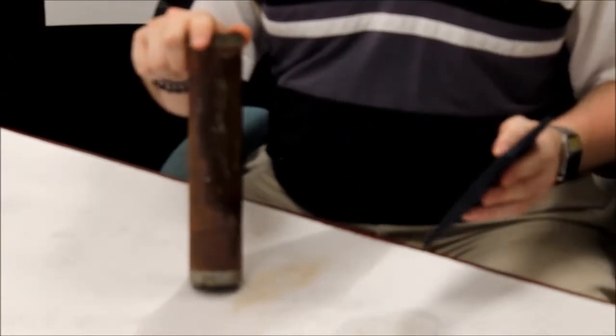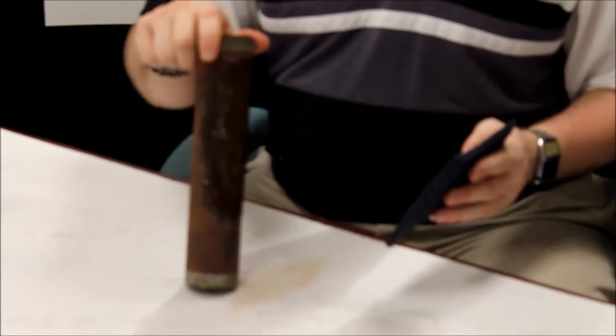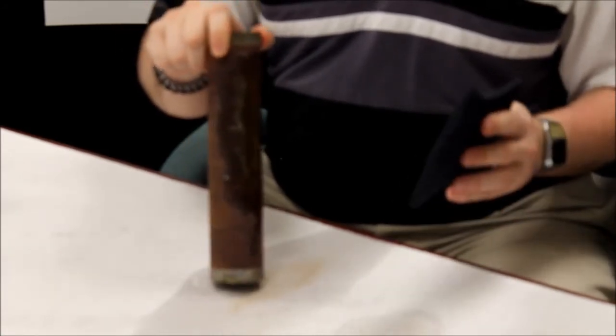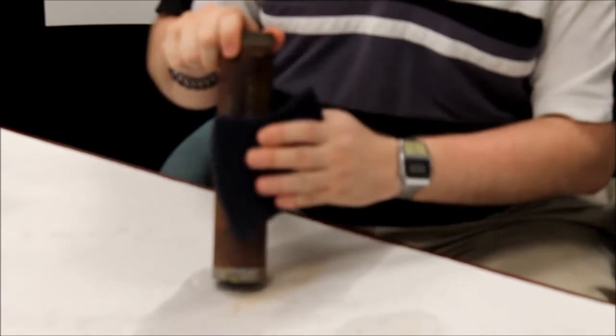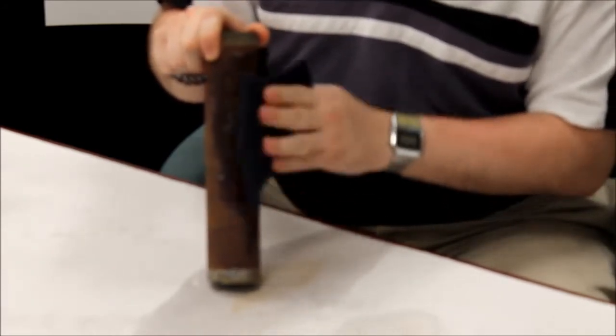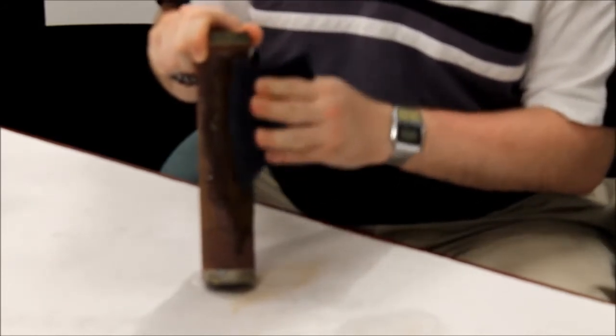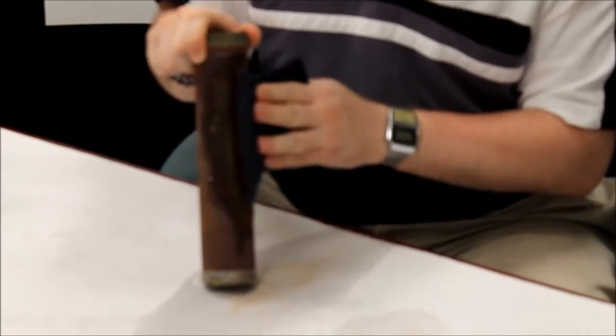If the rust is heavy, give it about 5 minutes or so to soak, and then you can help things out by scrubbing with a non-abrasive and non-iron containing pad to knock off the big chunks of rust. In cases of heavy rust, you also need to watch out for pitting. Pit corrosion creates small pinholes in the surface of the steel that will act as continuous sources of corrosion, even when you've properly cleaned and passivated the surface.